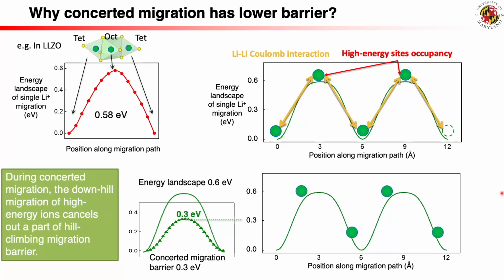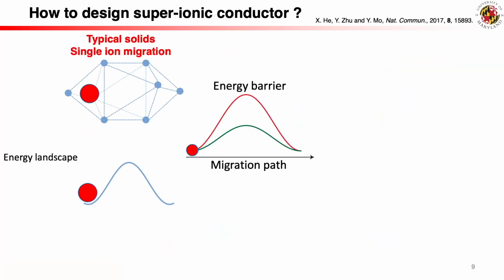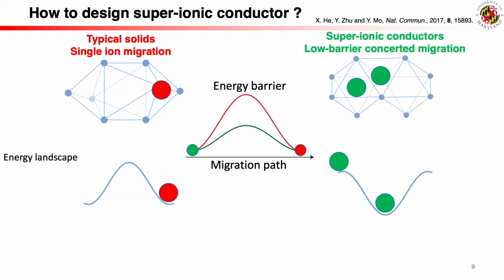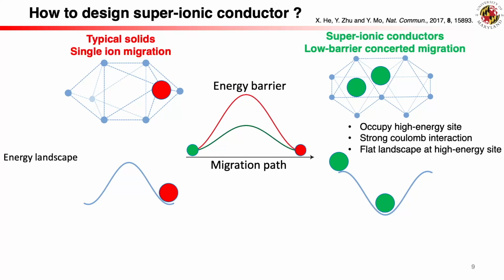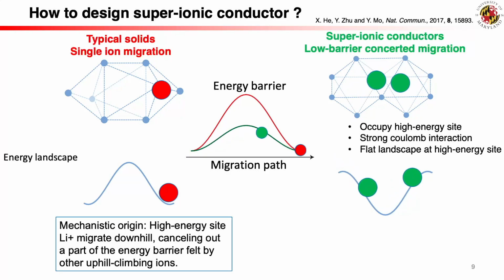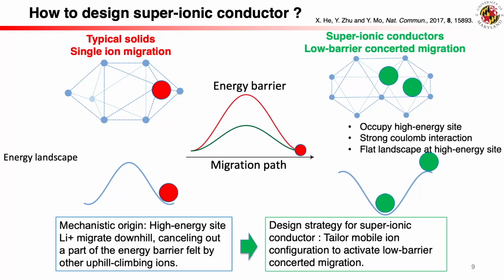Wow, that's exciting. And this understanding leads to a new strategy for designing SICs. Oh, tell me about that. The idea is to introduce mobile ions into high-energy sites to activate concerted migration and lower those energy barriers. So it's like a design principle. Exactly. And this explains why doping certain materials, like lithium garnet, can enhance their conductivity. Right, because you're adding ions to those high-energy sites.